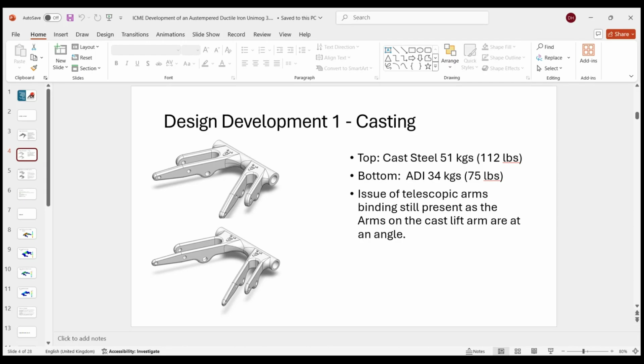So they did some design work, and they came up with 2 options: the cast steel, and then they found this material called ADI. The great thing about ADI was that it was very light. They managed to make this casting 34 kilos. Everything looked great until Atkinson Vos pointed out that the arms were still at an angle, so the hydraulic cylinders would still seize up over time.